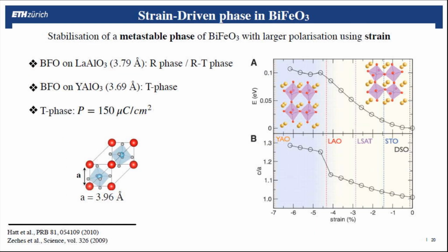So with that, I'll just show you now two applications with bismuth ferrite, just trying to motivate you that it's still a cool material, even if it's not ferromagnetic. So one possibility was done in this study, where bismuth ferrite was grown on top of a substrate. For the substrate, they have two types of material, which you can see here. And each material has a different spacing between the atoms. And usually what happens is that the substrate is the one that will impose the distance between the atoms in your material. So by having this substrate with these lattice parameters, so distance between the atoms, you can see that it's actually different from the one of bismuth ferrite.